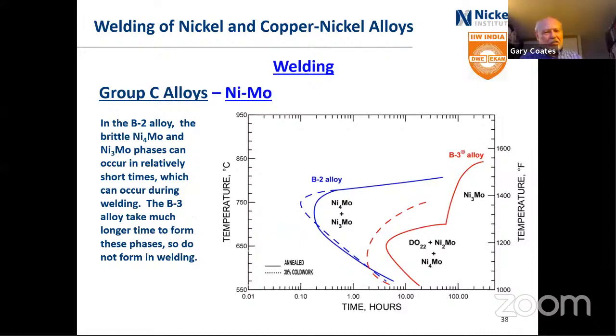Some of us love phase diagrams here, and this really just shows that the B2 alloy, you can get some brittle nickel molybdenum phases occurring in relatively short times, 6 minutes. Hopefully, during most welding operations, you won't be getting 6 minutes at 750 degrees C, but it is something to consider if you're doing any heat treatment on it, or if you need to do a lot of repair welding on it, where the B3 alloy takes much longer time to form these phases. So really impossible to form during welding.